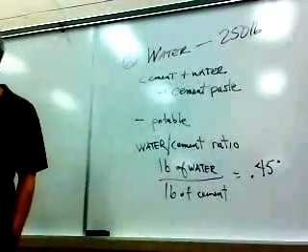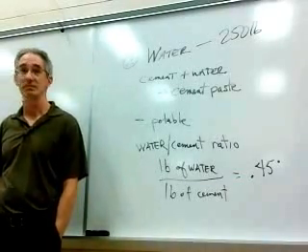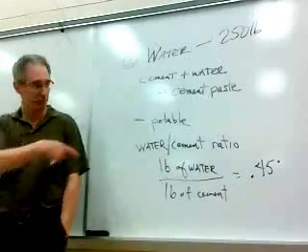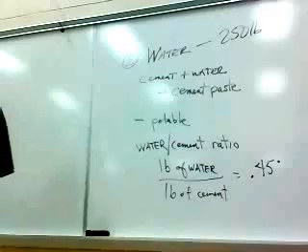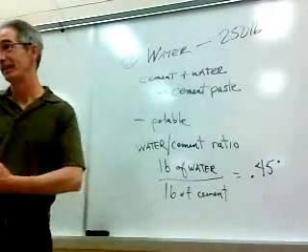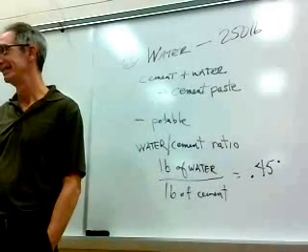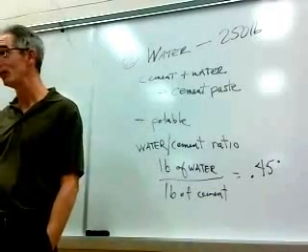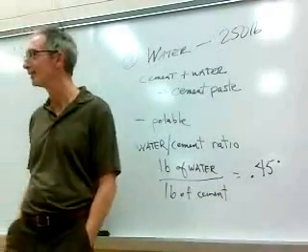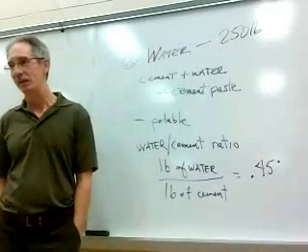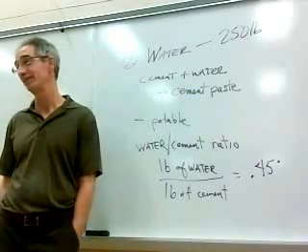You know how many pounds of cement? Well, if you just said 0.5 for water cement ratio, you'd say around 500 pounds. Now that's in a cubic yard. How many pounds is in a bag? 94. So probably the typical mix, if there is such a thing as a typical mix, has about 6 bags of cement in it. So that's when we talk about cement being expensive before, you can see probably why it's more expensive.